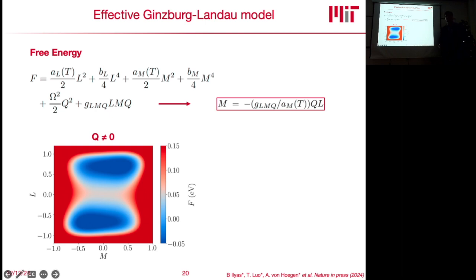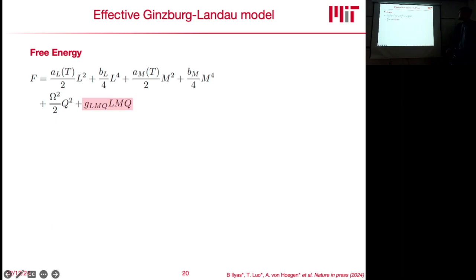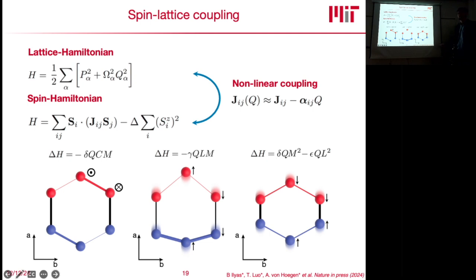But in this approach, do they think about the individual spins as being just constants? Like when you start, half of them is up and the other half is down, then L is equal to 1. Exactly. And then what is the picture when L is not equal to 1, when it's less than 1? They assume that the spin is 1/2, or like a macroscopic, integer number. However, these are basically macroscopic constants, which can then deviate from the integer value, at least in my understanding. So how is L defined in your case? You take the sum of all of these spins down and spins up, and you take the minus in between. So this is the antiferromagnetic order parameter in this case.